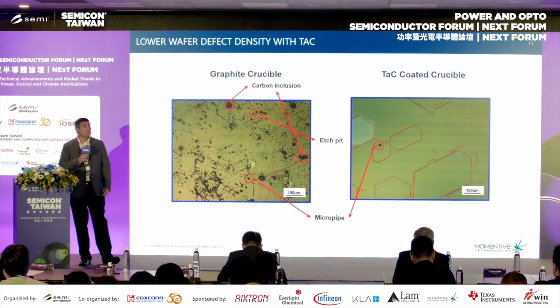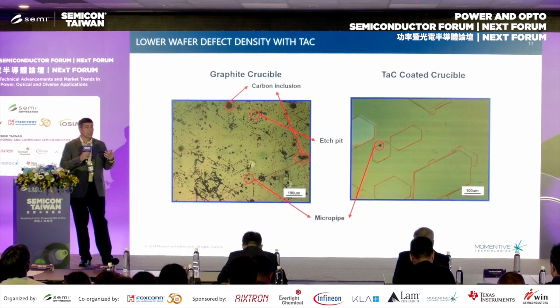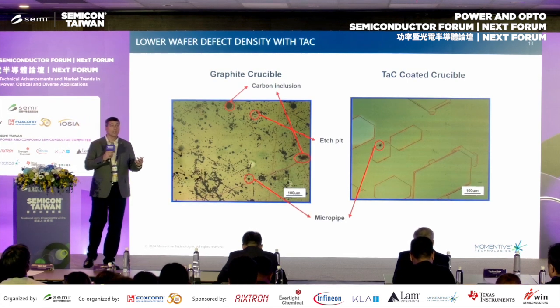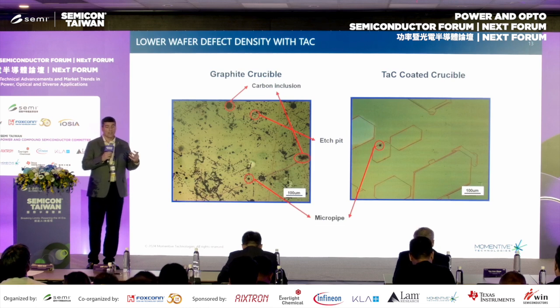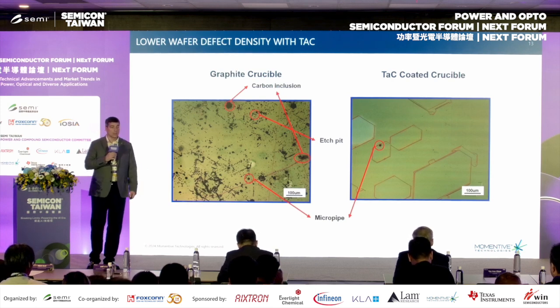One of the benefits of this really has been in going to the 200 millimeter. That's shown to be quite advantageous as you step up. So even folks that were at 150 millimeters getting away with pure graphite are shifting to more tantalum carbide coated as they go to the 200 millimeter.